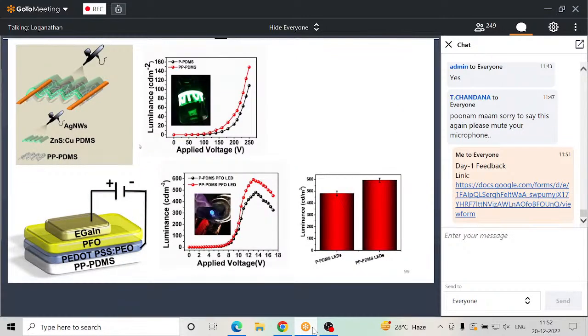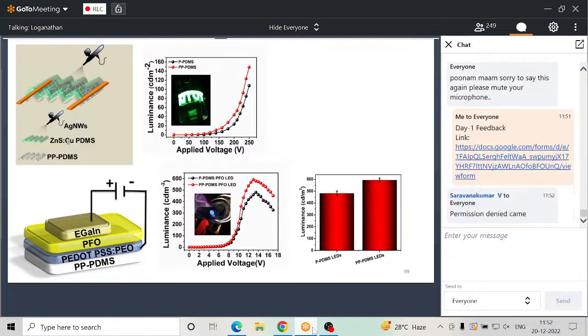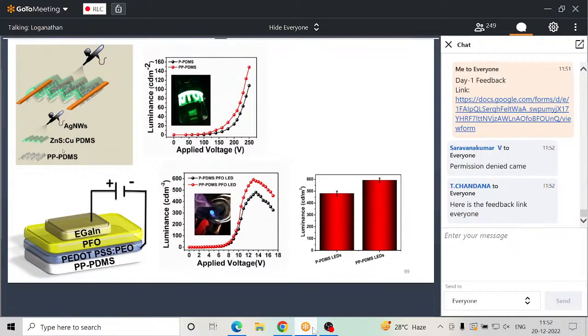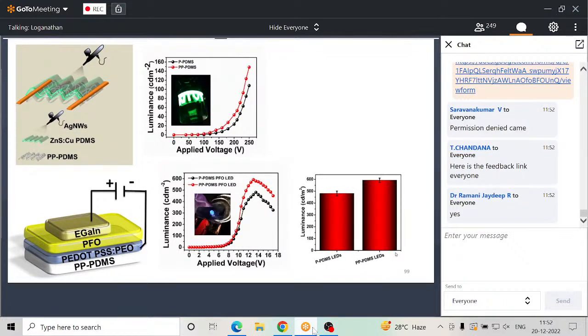And for the final demonstration, we did this to prove that this kind of electrode can be used for optoelectronics. So we made some ACEL devices with the conventional structures like zinc sulfide, copper structures, and then we also formed some PFO-based LED devices, and we studied the luminescence among pattern PDMS and PPPDMS. And from these results, we are pretty sure that microstructures are quite important for the fabrication of sensory as well as optoelectronic devices.